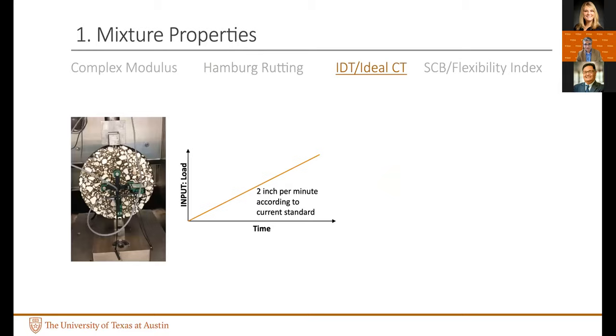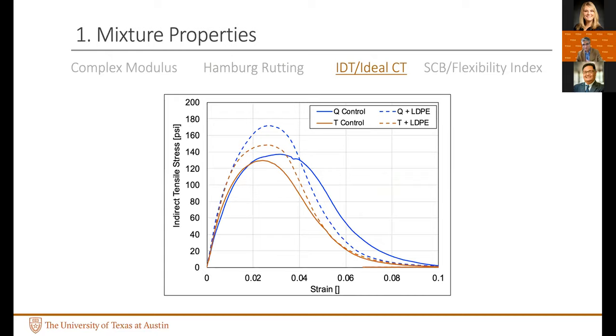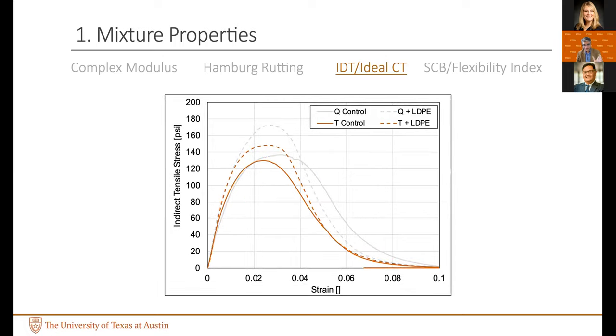The indirect tensile strength test, again, this is the standard test, except that we are also measuring displacement. And the ideal CT index and so forth, without getting into the details of the index, the two things to look at here would be the strength and ductility. So if you look at the tensile strength of the material, that certainly increases. And if you look at the ductility, although in this particular binder it looks like the ductility has increased, that increase is really small. But there's also a loss in the slope. So meaning it loses a little bit of ductility, but it gains a little bit of strength here.